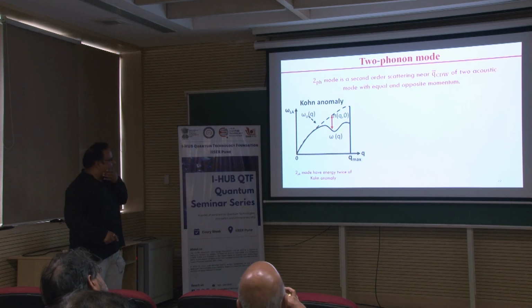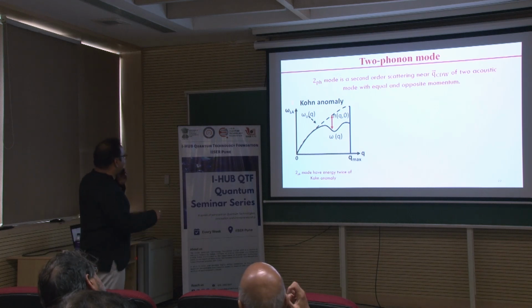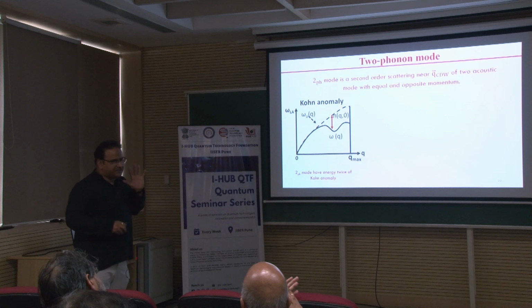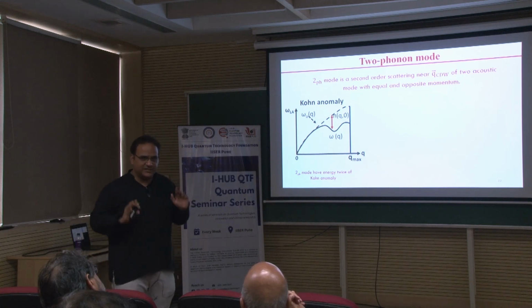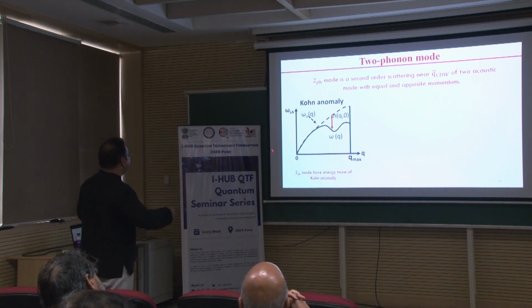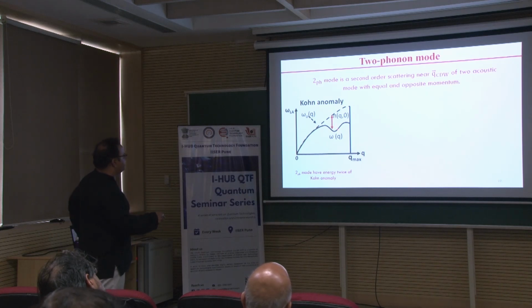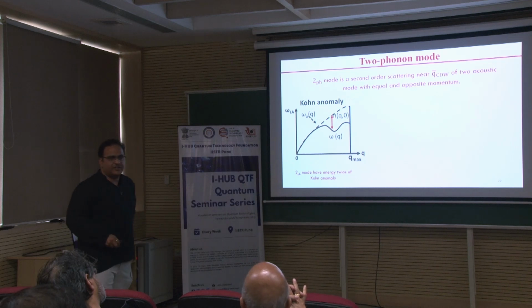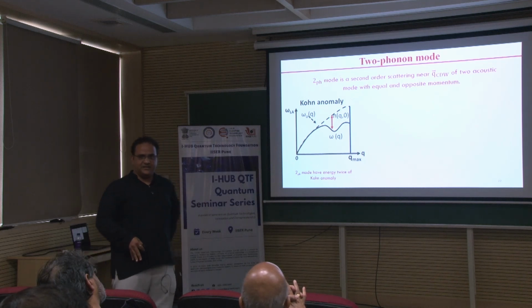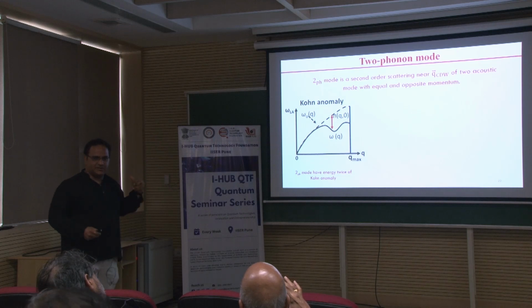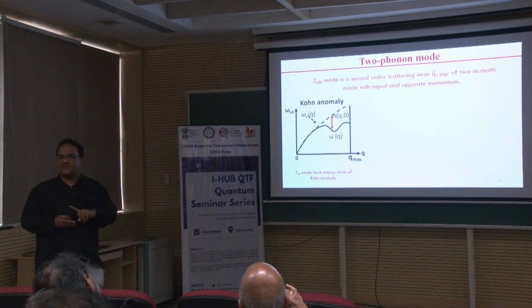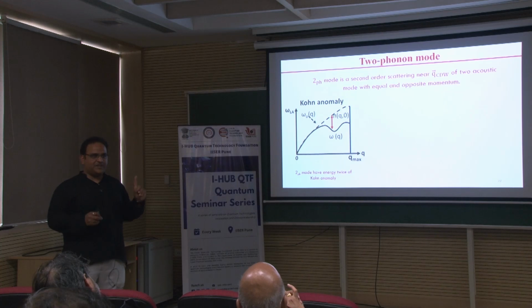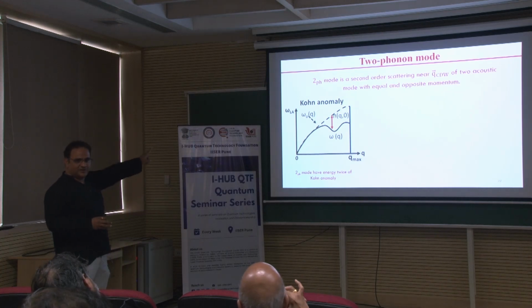Now, if you look at the textbook definition of charge density wave, it is associated with the Kohn anomaly. What is the Kohn anomaly? Right at the q vector where you have the charge density wave gap, this is the usual phonon dispersion for the acoustic mode. Right here you have an anomaly. There is a dip in the phonon dispersion, and that dip is the Kohn anomaly, and the energy of this Kohn anomaly is half of the 2 phonon mode. So the 2 phonon mode has an energy which is double that of the Kohn anomaly.